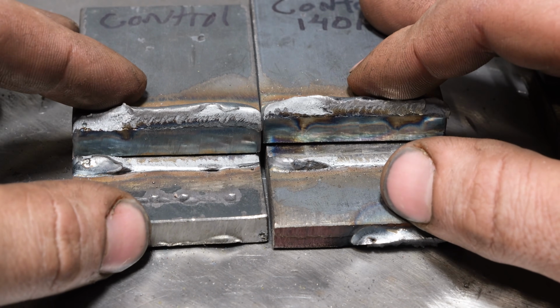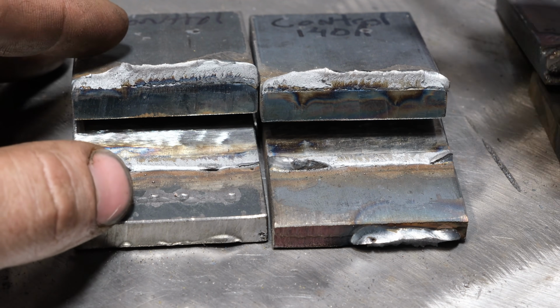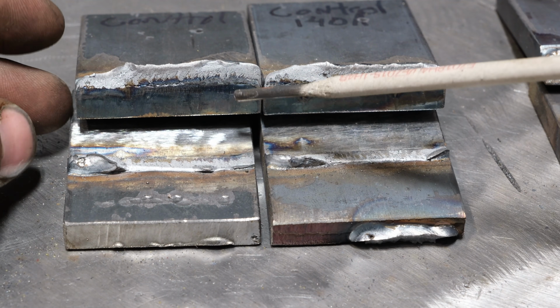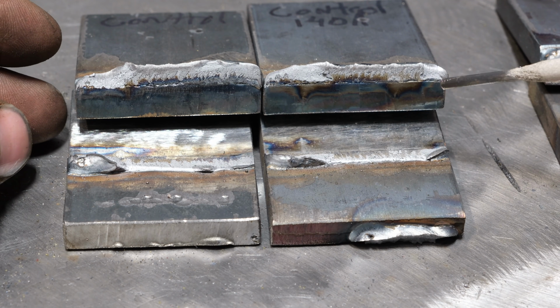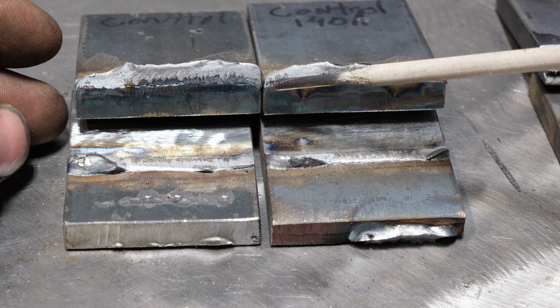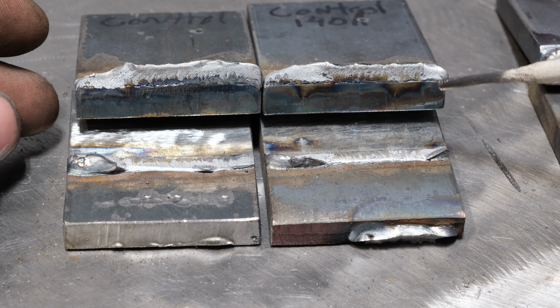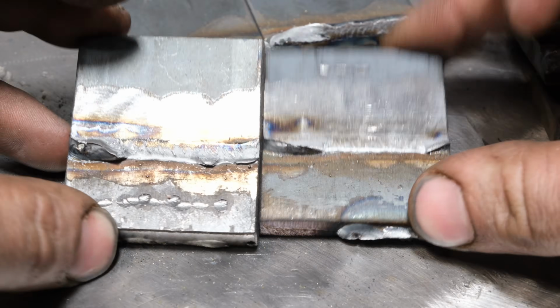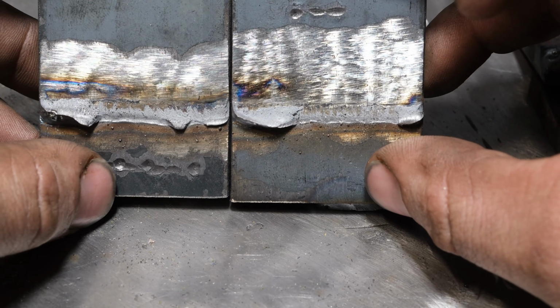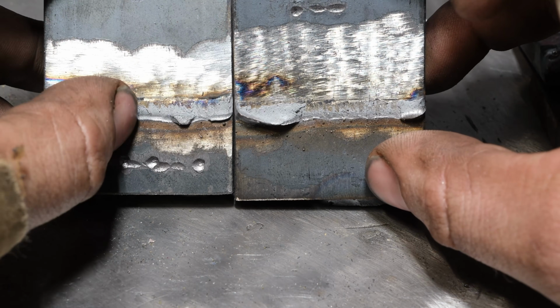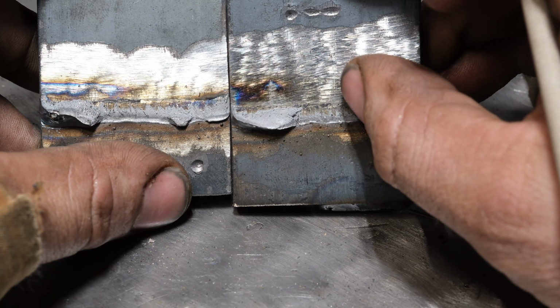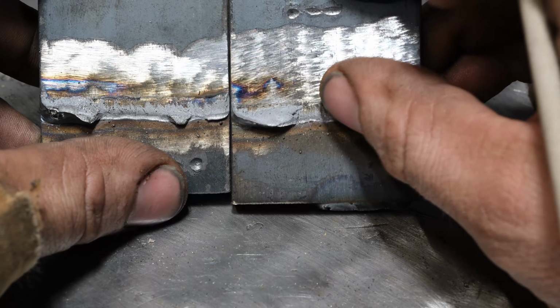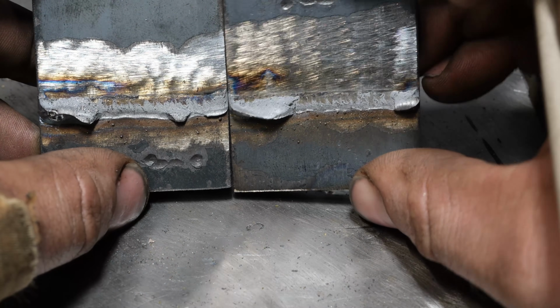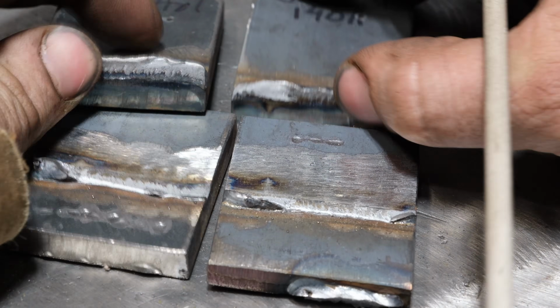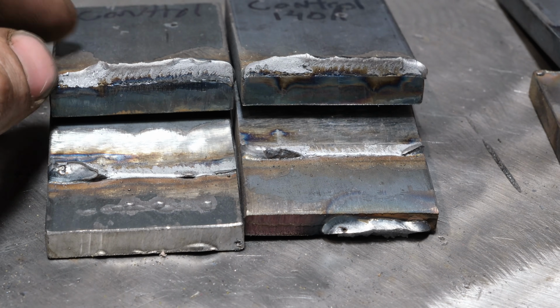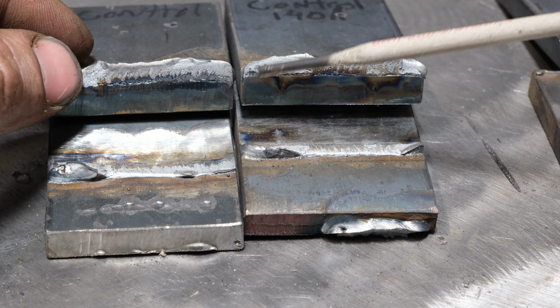So I brought out the control on the higher amperage to the control at 140 amps to compare and contrast right away. So you can see on this 140 amp, there is no breakdown of that root whatsoever, which is going to cost us significantly in strength. And when you look at the bottom plate, the fusion is even worse. So right here, it gets pretty narrow on this. That's not good, but here it's even more narrow with more of the polished plate edge showing. It's not a huge difference, but it's there. So this broke at lower values despite having similar size and weld, simply because of the lack of root fusion.